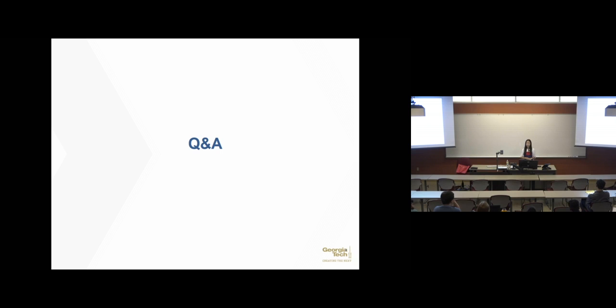That's a very good question. That depends on what size you want to probe, right? For the AFM measurement, I actually forgot to mention that we use a sphere about 25 micron, and the indentation depth is usually a few hundred nanometers to a few micron. But the early experiment that I showed you, this relaxation test that is in bulk shape, the sphere is centimeter size.